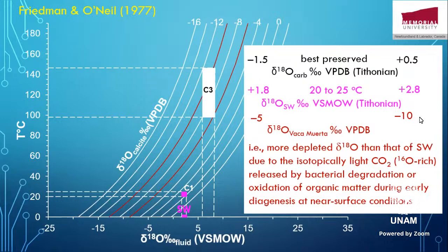But all the delta O18 of the Vaca Muerta is between -5 and -10 for the C1, for the lime mudstone. This doesn't fit any mixing of seawater or marine water. It's quite obvious you have values more depleted than that of this water, due to the isotopically light CO2 that came from the bacterial degradation or oxidation of the organic matter during the early diagenesis at near surface temperature. That's what caused that very depleted delta O18 of the lime mudstone.